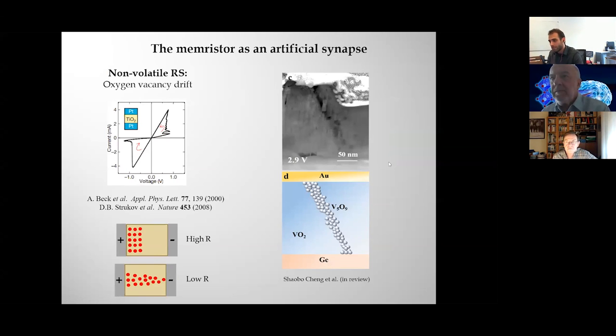Yeah, you could find a temperature range in which you would have this insulator, but it's still metallic, and at lower temperatures, both of them would be metallic. Exactly. Yes, that in principle would be possible. The only thing that would worry me is the variability between different cycles, because creating these filaments back and forth might be easier, but making them have an insulator to metal transition, I'm not sure how reproducible that is if you do it several times. But I'm not sure about it.